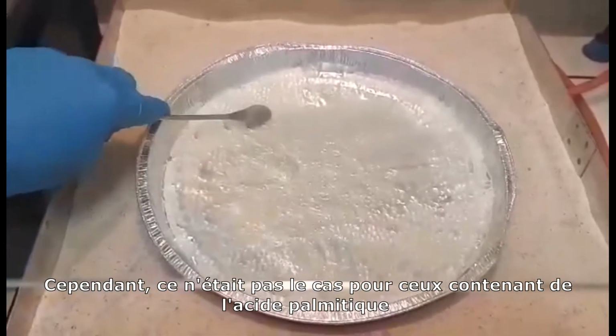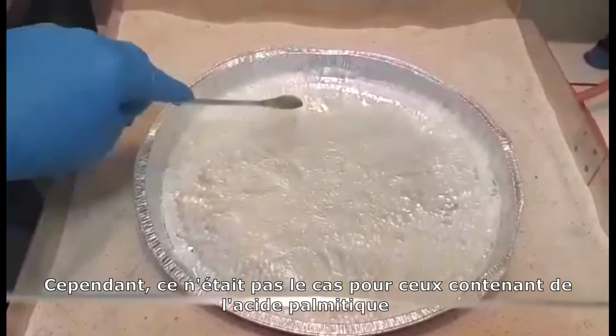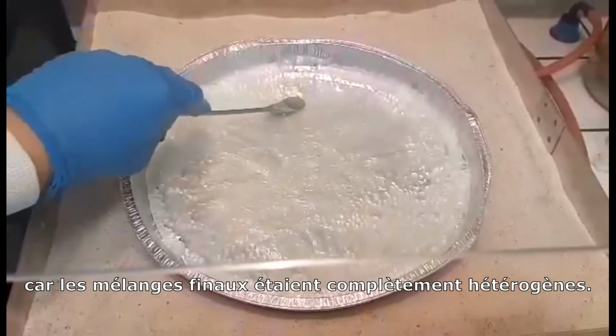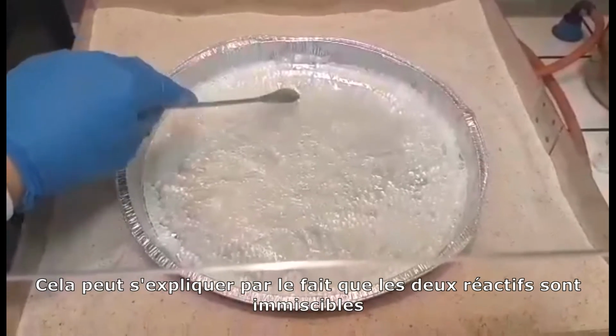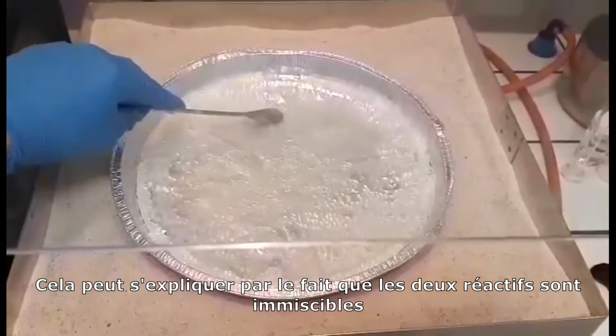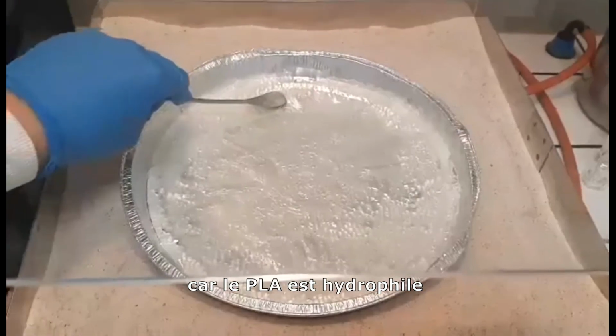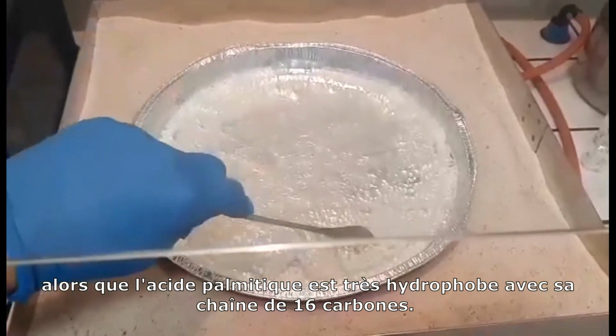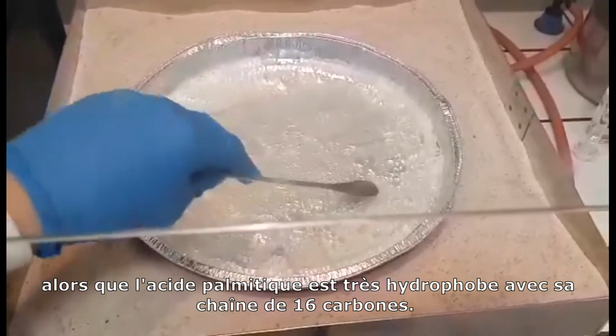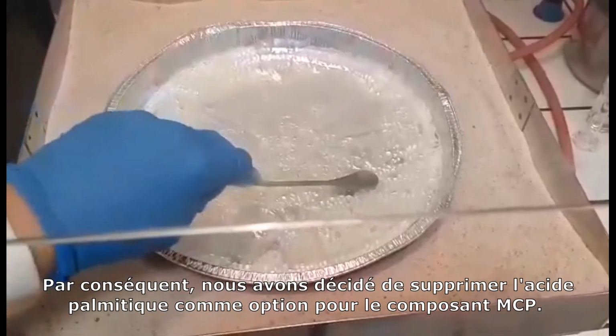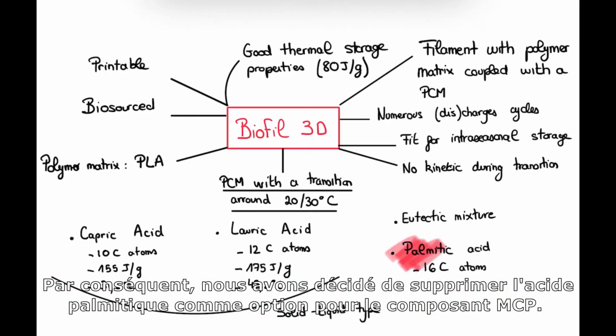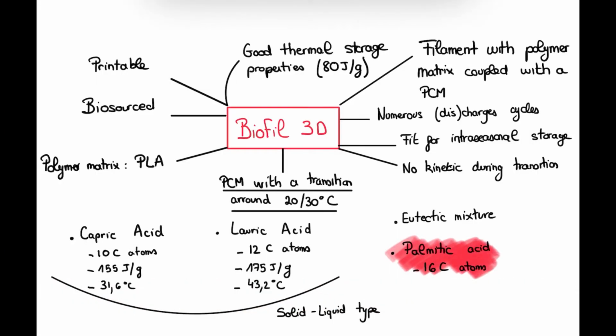However, it was not the case for the ones with palmitic acid, as the final mixtures were completely heterogeneous. It can be explained by the fact that the two reagents are immiscible because PLA is hydrophilic, while palmitic acid is very hydrophobic with its 16 carbon chain. Therefore, we decided to remove palmitic acid as an option for the PCM component.